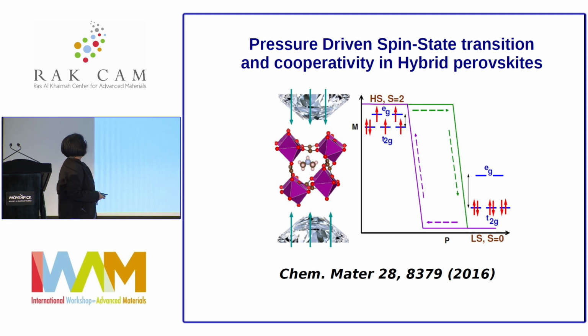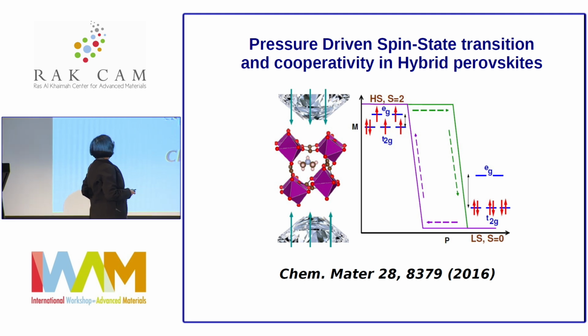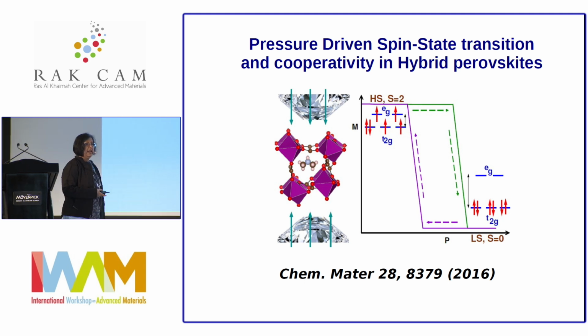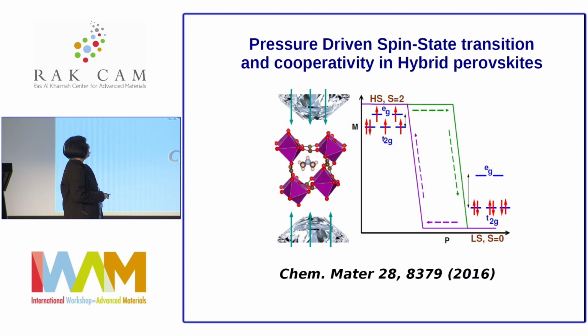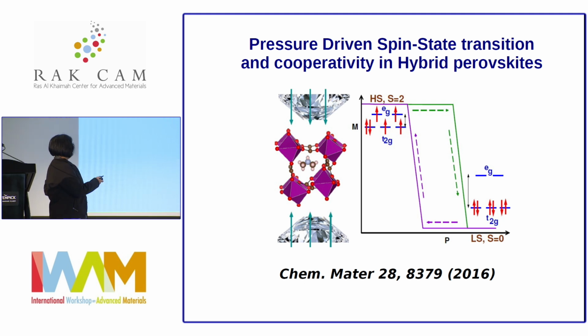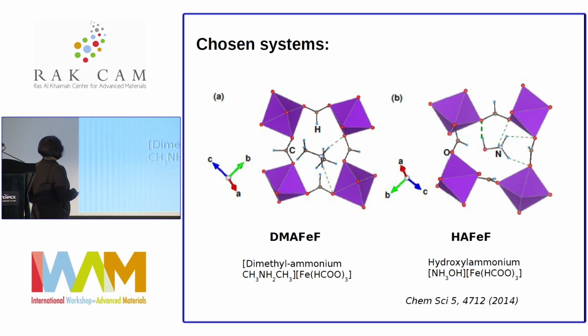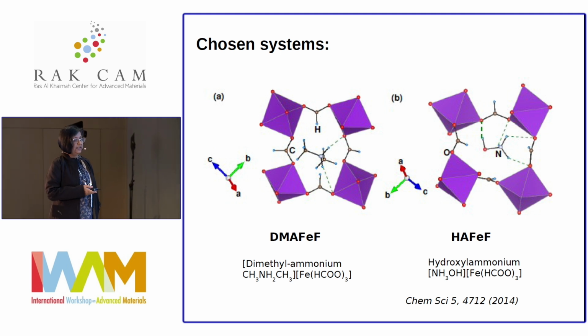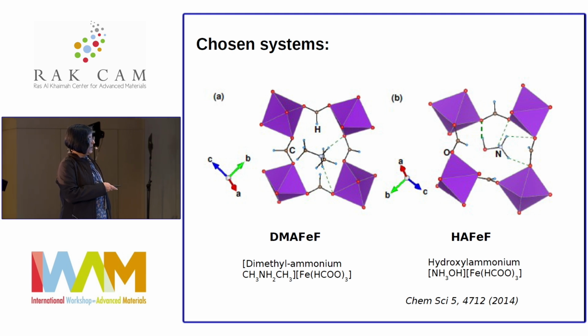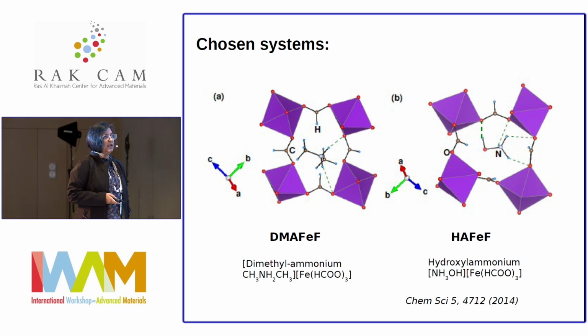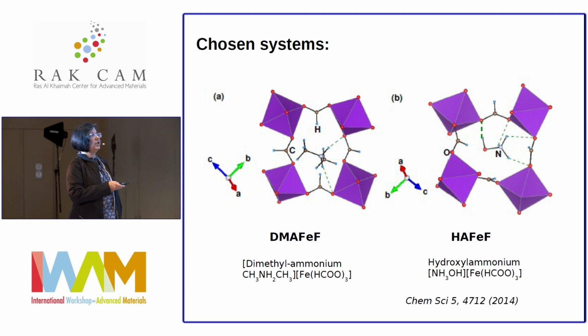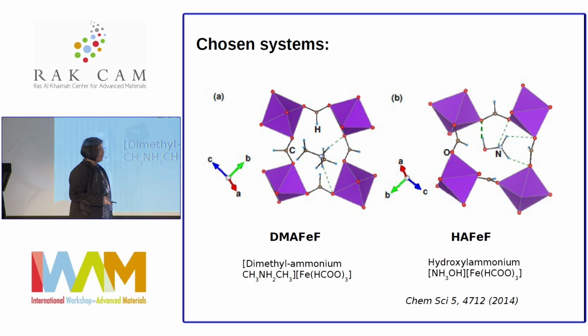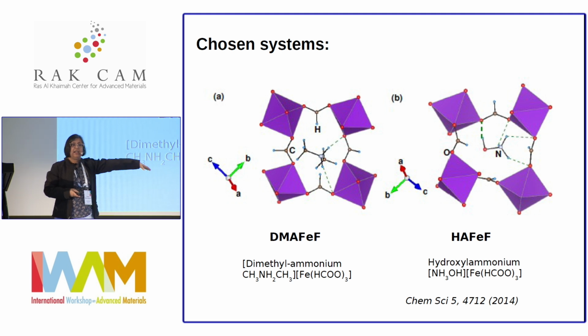And a few years back, together with my PhD student, Hrishit Banerjee, we made this computer experiment and indeed showed that there can be pressure-driven spin state transition together with this hysteresis effect. And for that, these are the systems we looked at. So they are all protonated amine at the A site, as you all know. So we considered 2 different kinds of this A cation. One is dimethyl ammonium, another is hydroxyl ammonium. And the manganese version of both these compounds have been synthesized, but not the iron one, at least not in the ordered phase. But we considered really the ordered phase, and if you can make it ordered by this hydrogen bonding, you should be able to see this effect.